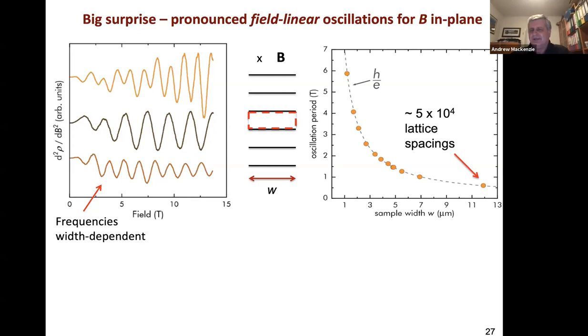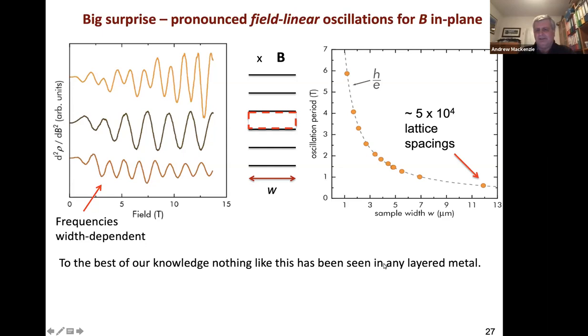So what we're seeing is some kind of a quantum coherent effect there, persisting to quasi-macroscopic length scales. And obviously a prerequisite to that is to have an extremely pure material where you don't scatter that coherence away with your disorder. Now, it's always interesting how sociology works, when you see something that, as far as I know, was completely new. I don't think anything like this had been seen or has been seen in any other layered material. People have very strange reactions to it.